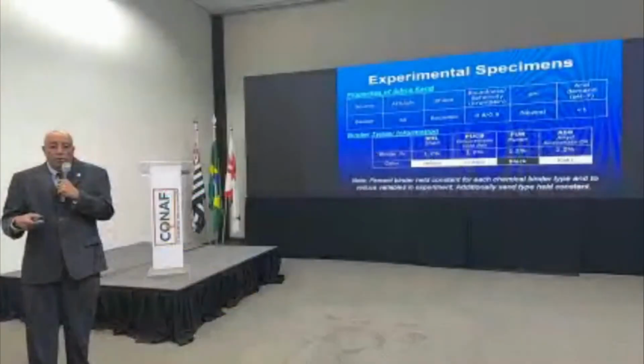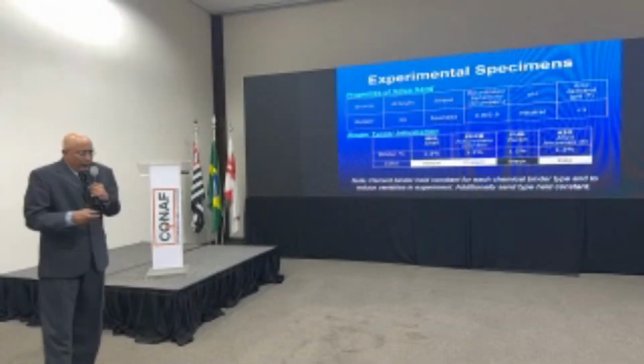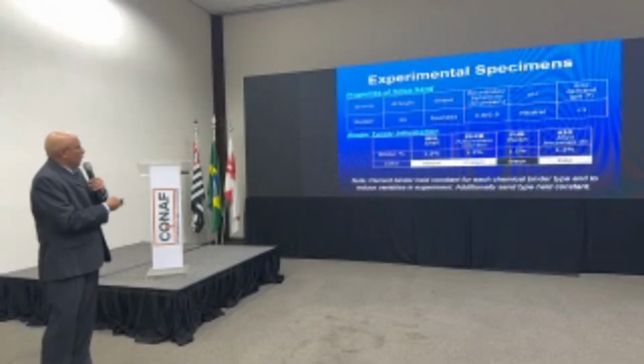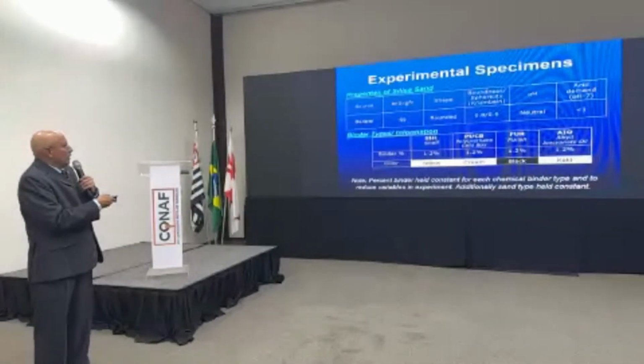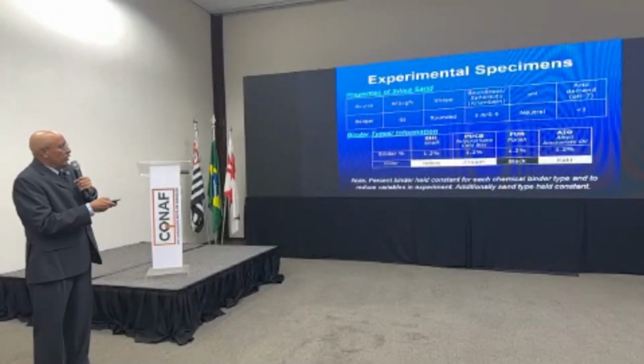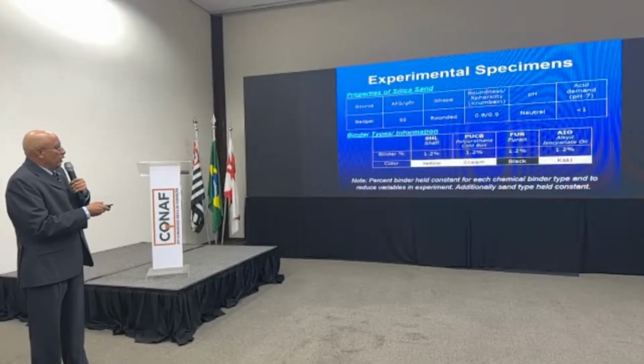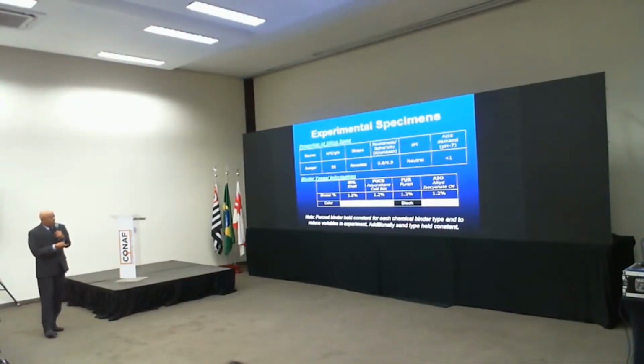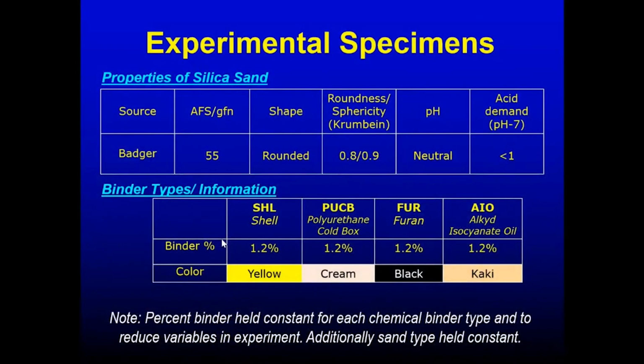We have data from a thermal distortion curve. So here I'm showing you, for example, 4 different sand binder systems. The sand is the same size and distribution in all cases. It's the same sand, but we're using a shell hot box system, a urethane cold box system, a furan system similar to what is being used in 3D printing, and an alkyd isocyanate oil that would be more common in no-bake systems. And the percent binder is held constant for each. The only reason that we're keeping the binder constant here is so that we do not indict any chemistry.